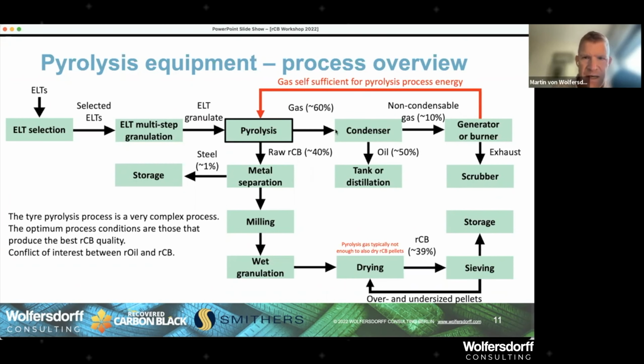Then we are in the pyrolysis, and what comes out of the pyrolysis at that point is a gas, and we can say it might be some 60% of the output of the reactor. That gas in a condenser can then be split into a condensable gas, which we can call oil, which will be about 50%, and that goes into a tank or a further distillation treatment, and then the remaining gas, which could be 10%, goes in a burner or a generator. The exhaust you might need to scrub because there's a sulfur content. Some modern processes actually now scrub the gas before it goes in the generator or burner because the sulfur content is also dangerous for the burner.